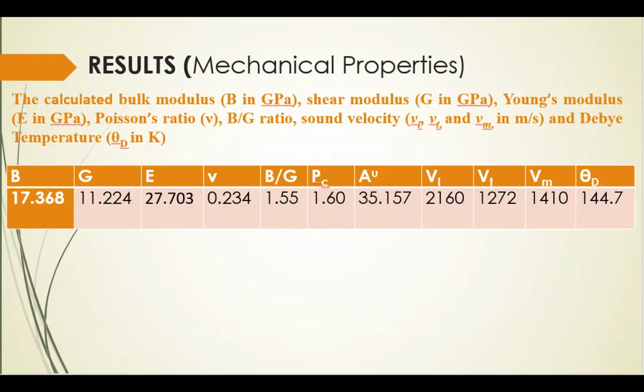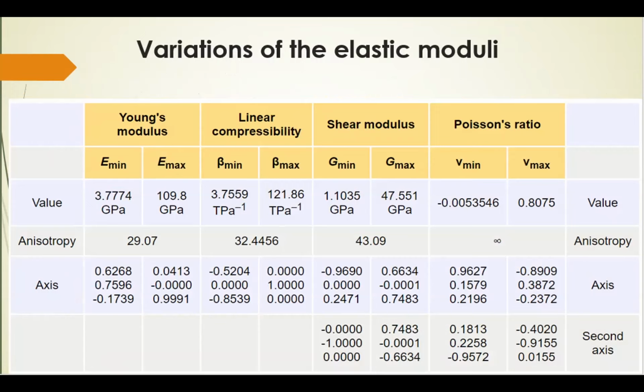Young's modulus is related to the hardness of the material. It was observed that it was not very high in these materials. According to this, we can say that the material has a soft character by looking at the Young's modulus. It is seen from the Poisson's ratio that they have an ionic bond structure. From the B/G ratio, it is predicted that the compound is brittle.